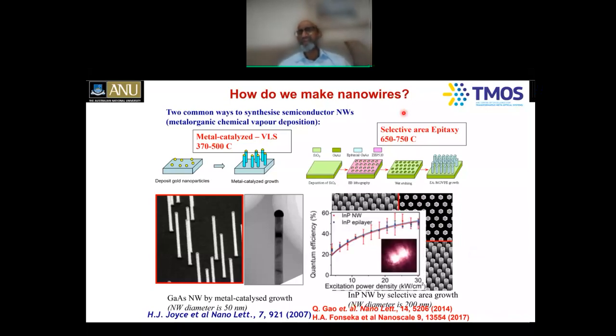We have taken these indium phosphide nanowires, excited them with a laser pulse, and looked at the light coming out of them, and we try to quantify the photoluminescence. We quantify the quantum efficiency of the light coming out of these indium phosphide nanowires and compare it with indium phosphide epitaxy layers, or two-dimensional layers, which we normally use for making a wide variety of optoelectronic devices. You can see that you can get quantum efficiencies as high as 50% or so, which of course depends on the excitation power density of the laser. The quantum efficiency of the nanowires and epitaxial layers is very comparable, indicating that surface non-radiative recombination is not a major issue in the case of indium phosphide. That means the broken bonds on the surface atoms of indium phosphide don't give any defect states that lead to non-radiative recombination.